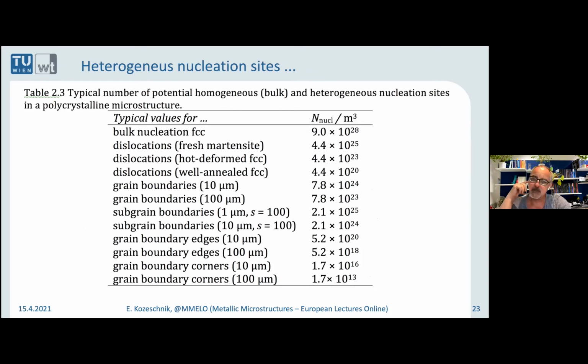And this is a table which I was calculating many years ago, where you could see, for instance, if you consider that every atom in 1 cubic meter of material is a potential nucleation site, then you can see that for homogeneous nucleation, you have roughly 10 to the power of 29 sites. If dislocations are favored nucleation sites, then we are orders of magnitude smaller already, depending on how many dislocations are available. Grain boundaries, of course, very much dependent on the grain size. The subgrain boundaries, if you have elongated martensitic grains, and if just grain boundary corners are favorite sites, you can see that the number of possible sites is decreased by many orders of magnitude.